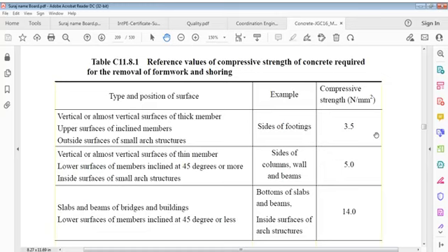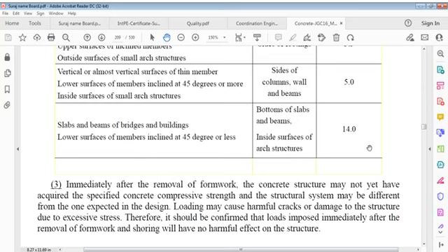The table gives type and position of surface and example compressive strength in Newtons per square millimeter. Vertical or almost vertical surfaces of thick members and upper surfaces of inclined members, outside surfaces of small arch structures, and sides of footings, for example, 3.5. Vertical or almost vertical surfaces of thin members, lower surfaces of members inclined at 45 degrees or more, inside surfaces of small arch structures, sides of columns, walls and beams, that's 5. Slabs and beams of bridges and buildings, the lower surface of members inclined at 45 degrees or less, bottom of slabs and beams, 14.